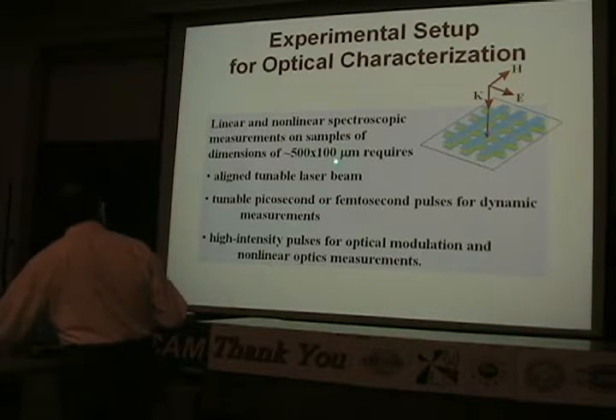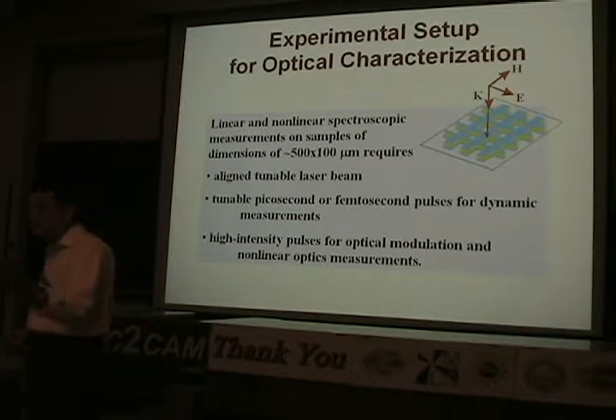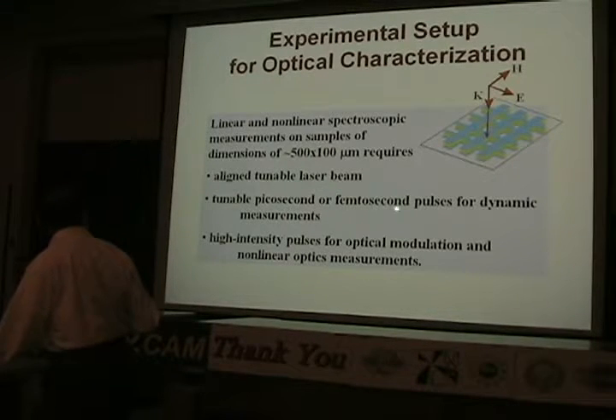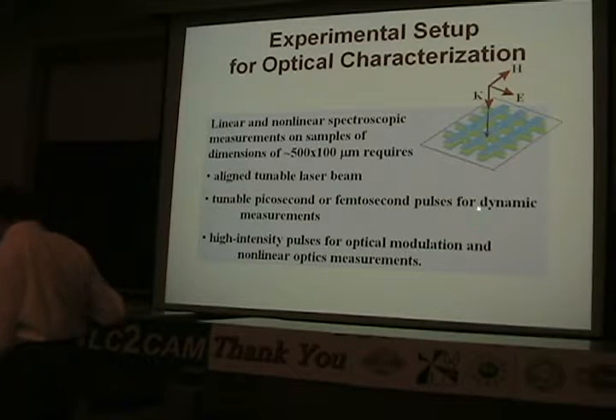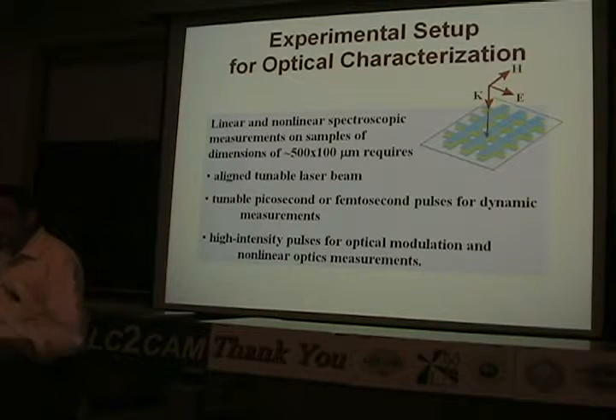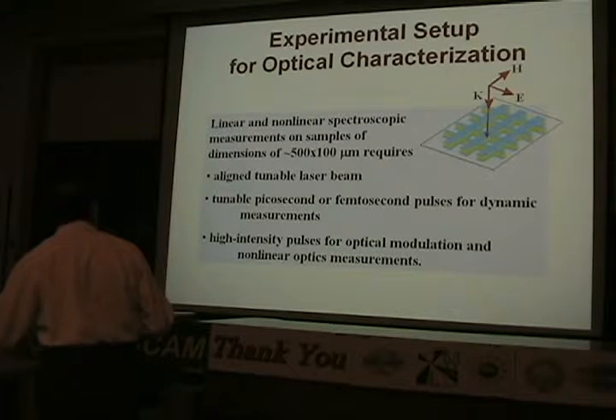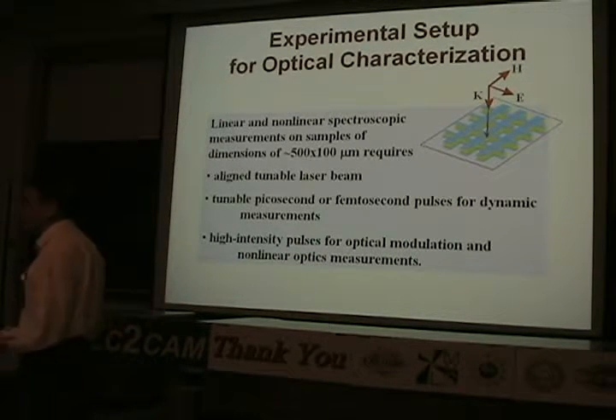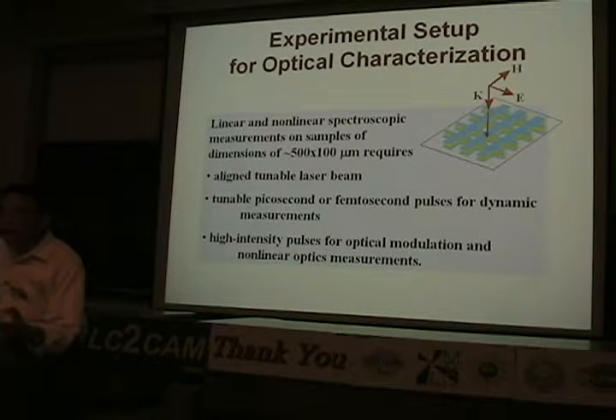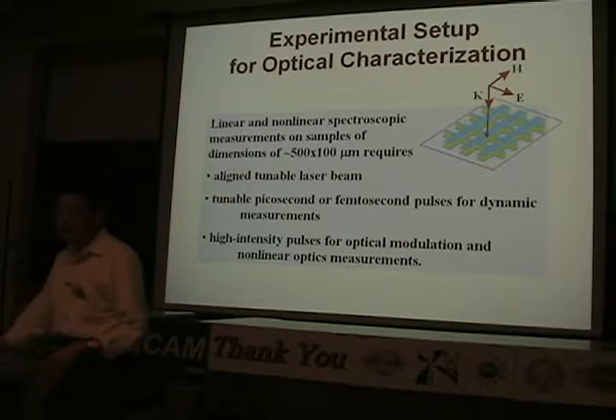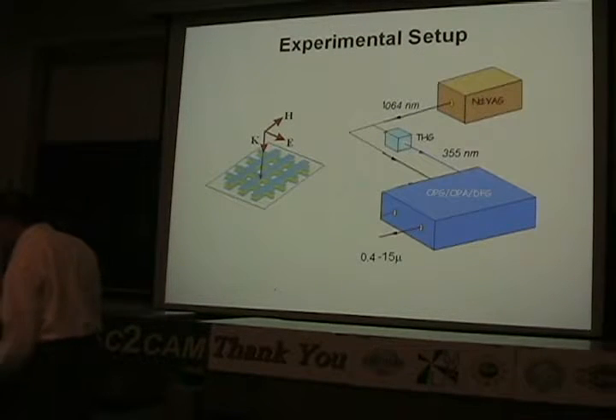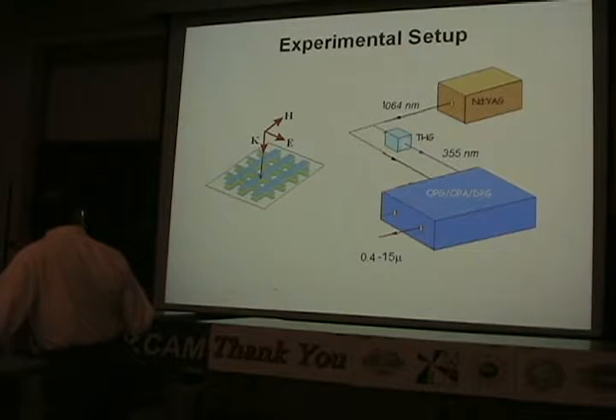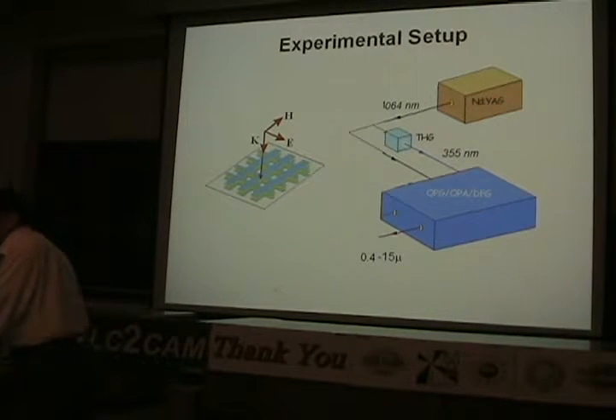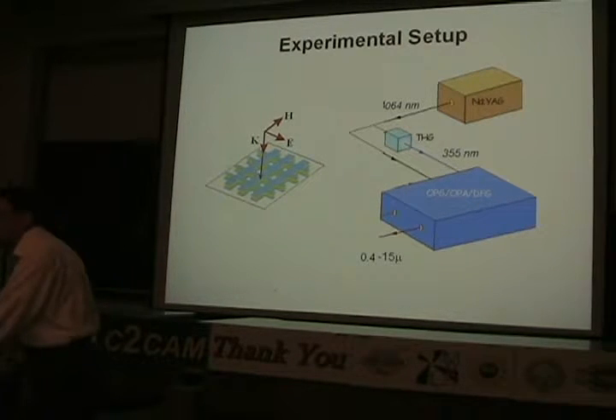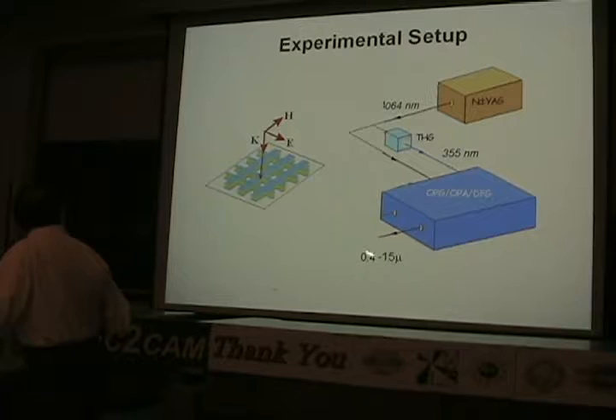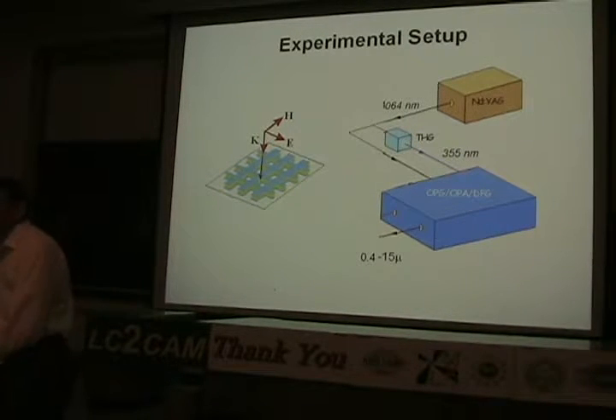And because we want to do spectroscopy, we need a tunable laser. And because we want to do optical switching modulation, we need pulse lasers, femtosecond and picosecond lasers. And for modulation, we also need to induce sufficiently large delta n. Therefore, we need a high intensity pulse. So here is one of the setups. We just use a picosecond YAG laser that pumps the optical parametric system that allows us to tune from 0.4 to 15 microns, so that covers the whole range easily.